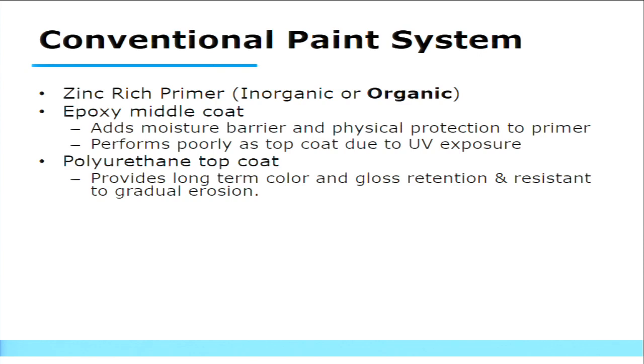So the conventional paint system would be our three-coat paint system that's been around for a relatively long amount of time. It consists of three coats, the bottom coat being a zinc-rich primer, inorganic or organic. Notice that I've highlighted organic, and that's our general recommendation, and I'll touch on that again later. The epoxy middle coat is mainly a moisture barrier, but it doesn't perform very well for UV exposure. So it can discolor. So therefore we use a polyurethane top coat, and that generally acts as our UV protectant, and it retains the color and the gloss longer.